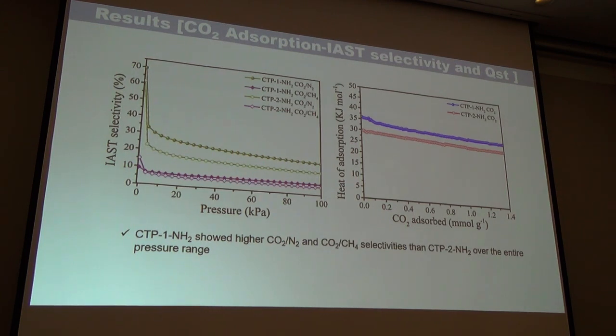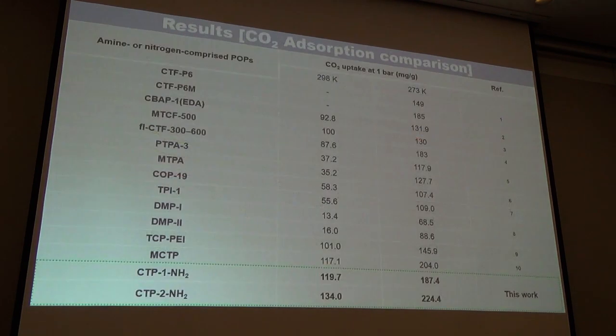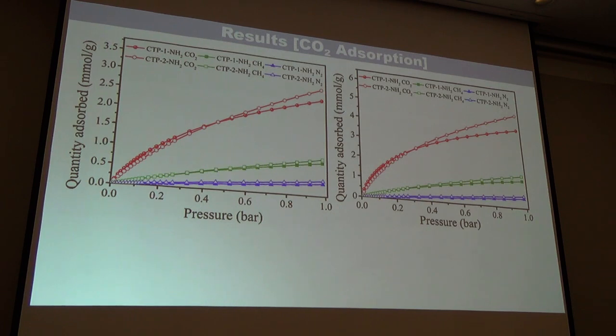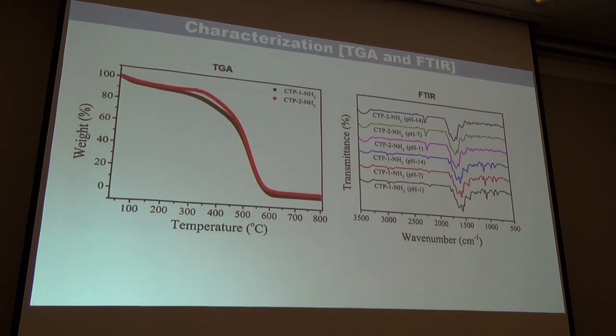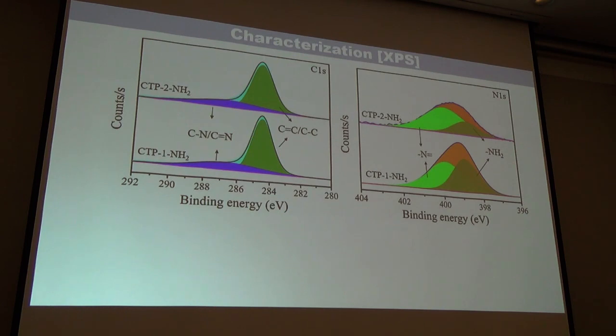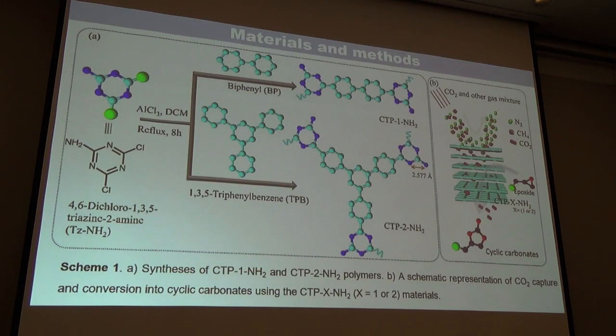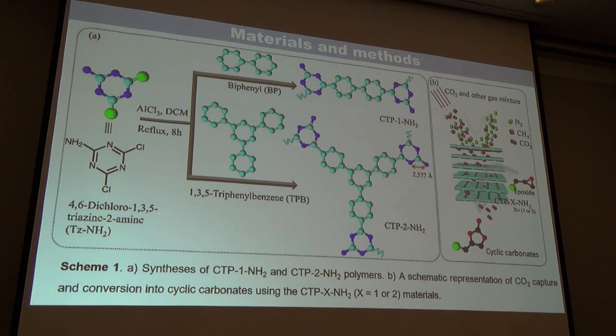We think the difference is because of the nitrogen content in the material. Because if you see the CTP1 material, we have used the biphenyl as an aromatic linker. So if you take this carbon content, in the end, the CTP1 has a high nitrogen content. When we have a high nitrogen amount, the adsorption of CO2 is also high in that low pressure region. So that made the difference between these heats of adsorption.